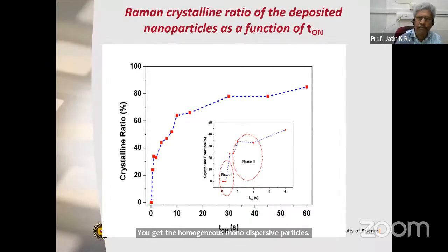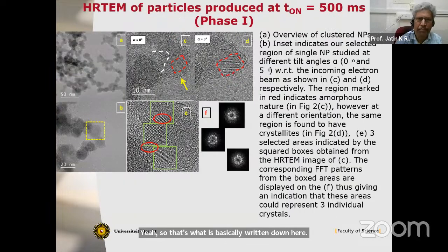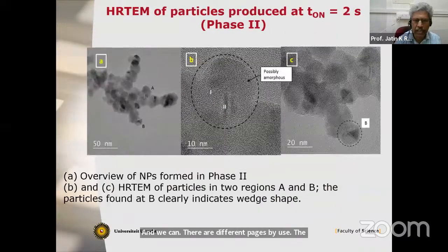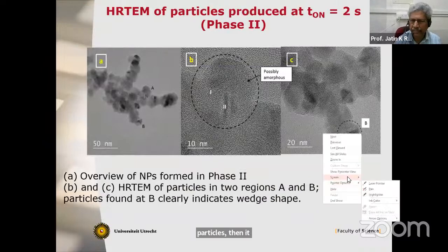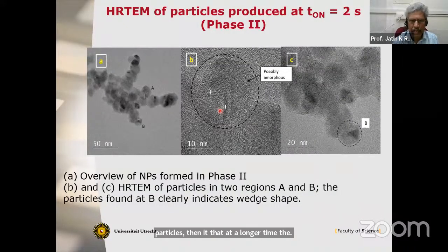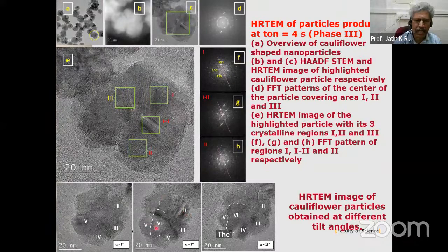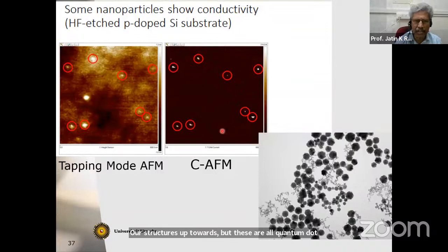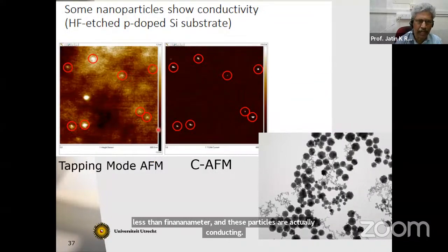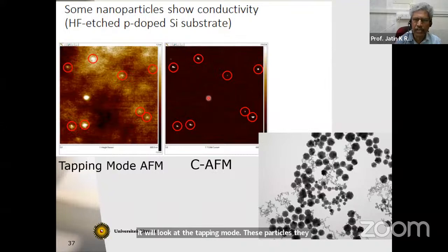And there are different phases by which the particles grow. First they grow as small particles. Then at longer times, the particles start coagulating and become cauliflower structures afterwards. But these are all quantum dots still, because the particle sizes are less than 5 nanometer. And these particles are actually conducting. If you look at the tapping mode, we did the conducting mode, they are all conducting. So these particles are real crystalline particles, and they can be used in solar cells. So we have been successful in making silicon quantum dots.